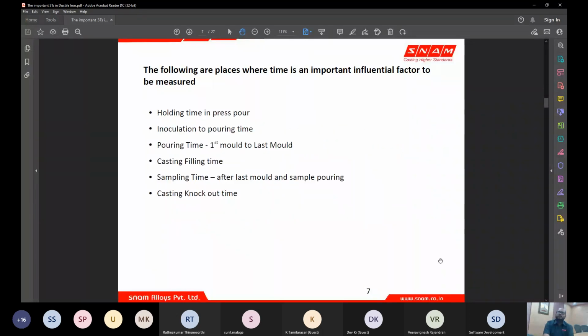Next, holding time in the press pour. This time we'll be talking about the time taken where the liquid metal is held in the press pour or any automatic pouring line, after coming from tapping and just before filling. If the treated ductile iron metal is held in the press pour for a longer time, you start getting a lot of reaction products, which are supposed to go into the mold and become good ductile iron. It will start reacting and start losing its potency.